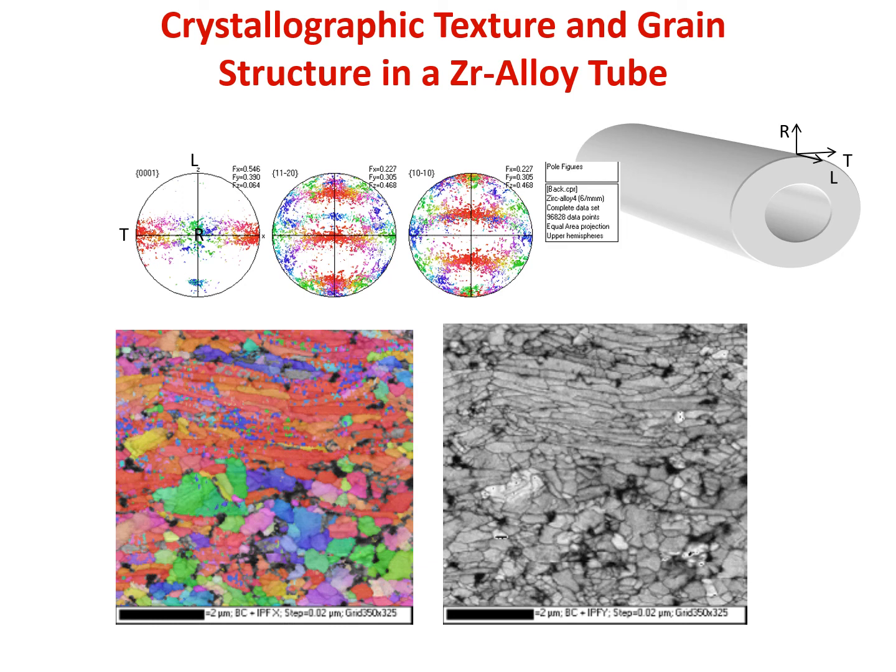So what you can see here is on this pole figure, there are a number of grains, these platelet grains here, which tend to have their orientation out in the transverse direction. The fatter grains here tend to be clustered around this orientation. We've known this for a long time, but this is just a confirmation of it. It just shows you how the texture is built up. So grains which are more equiaxed tend to have a strong radial orientation, and grains which are more platelet-like tend to have a strong transverse orientation.